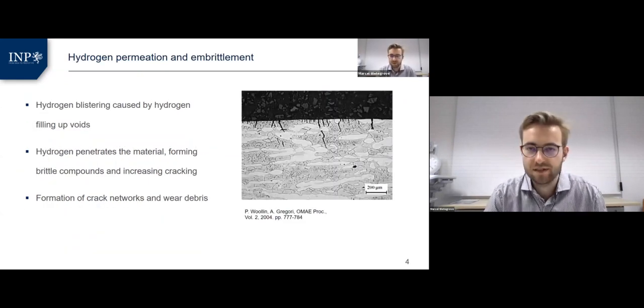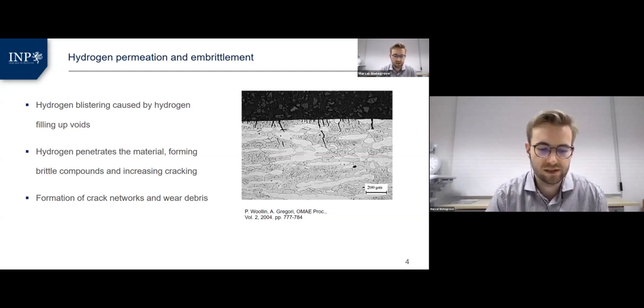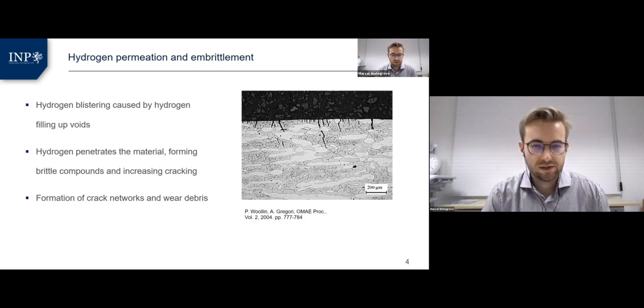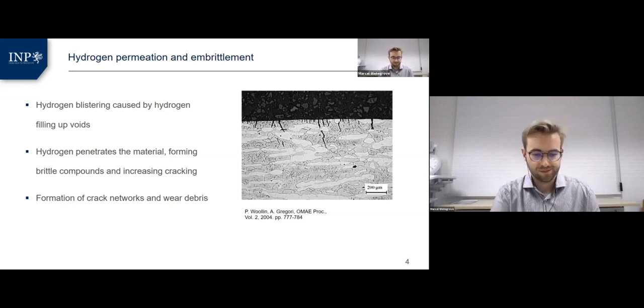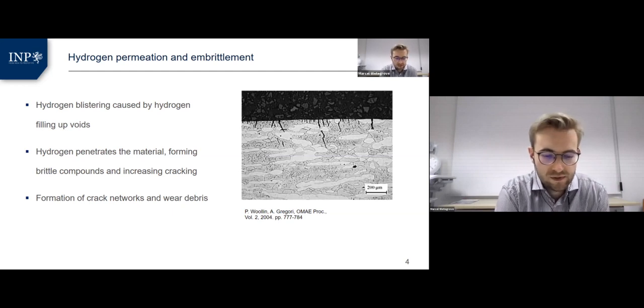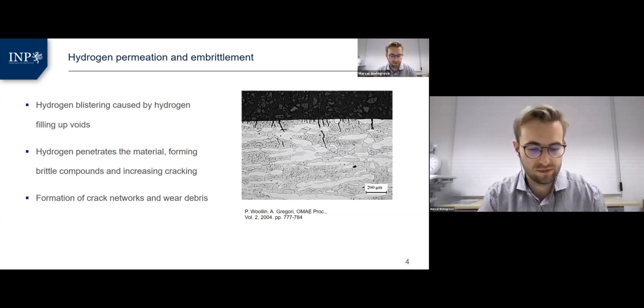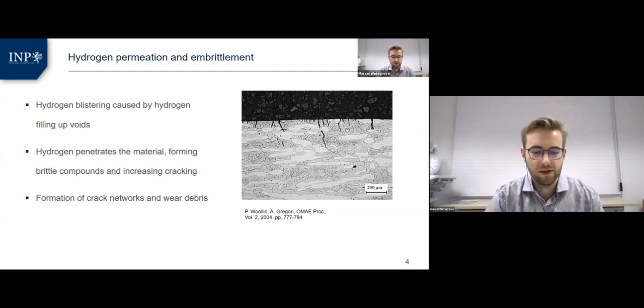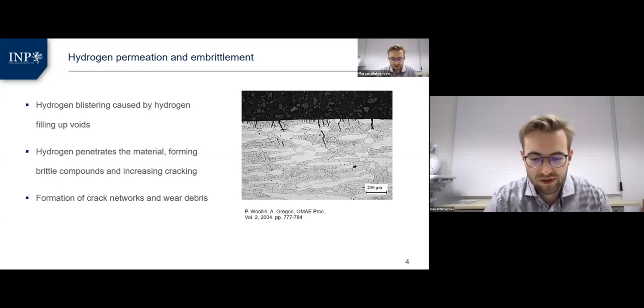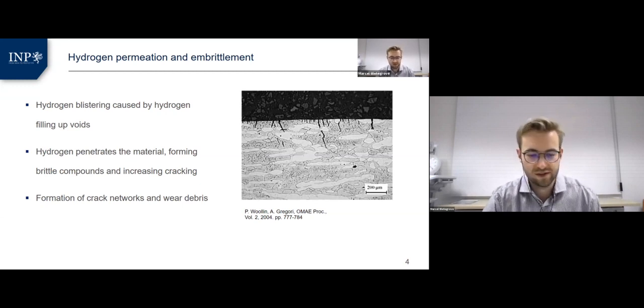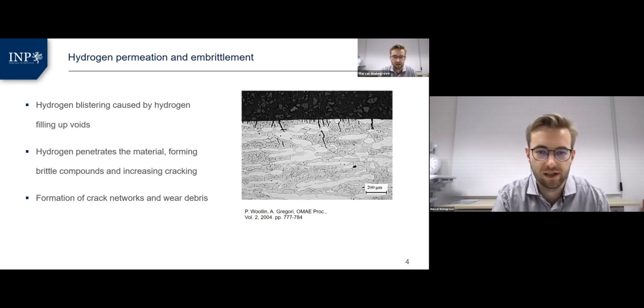Hydrogen embrittlement includes various effects that lead to the weakening of the material under the influence of hydrogen. And here not only the diffusion properties play a role, but also cohesive forces inside the material. The hydrogen interacts with oxide layers or metal atoms at the interface with the gaseous or liquid medium, and they make up important factors influencing hydrogen embrittlement. Also, the absorption behavior of hydrogen on the surface has great influence, and in addition to this, the diffusion of absorbed hydrogen, which can be further enhanced by factors such as stress or temperature, leading to the formation of crack networks and debris.